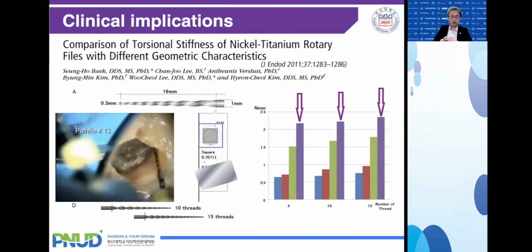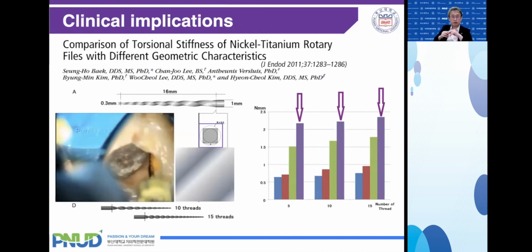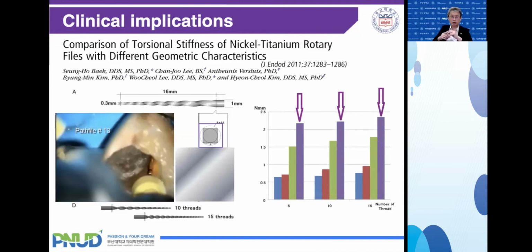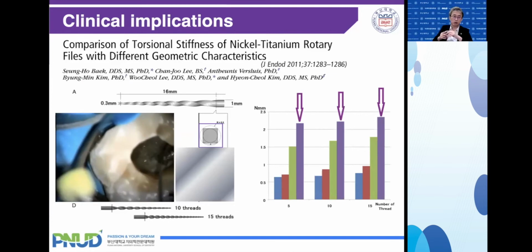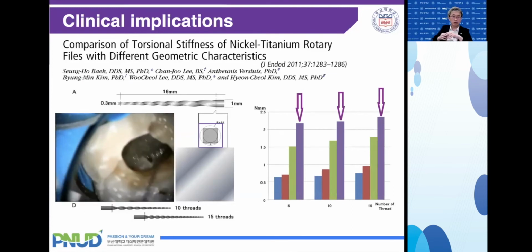The PathFile, you are familiar with this. You may know this, right? The PathFile has a square cross-section, and the square has the highest torsional strength from this study. As you know, the taper of the PathFile is just 2%. It is a very thin and tiny file. When we use this in a very calcified small canal, it can endure without any fracture. It's not so easily broken. The reason why this thin and tiny file resists fracture is the square cross-section. If this PathFile had a triangle or other cross-sectional shape, it could be broken more easily. I think the square shape is a good decision for this PathFile.